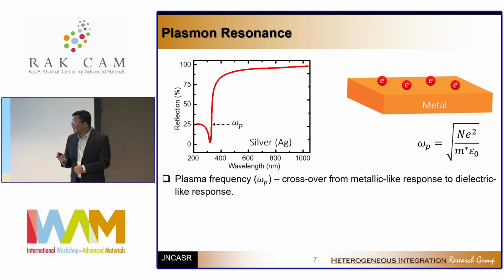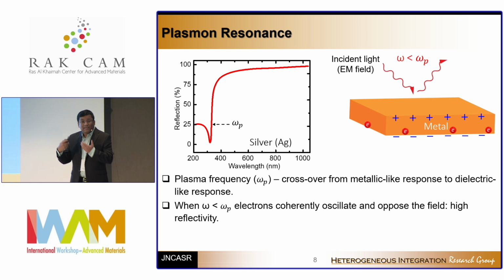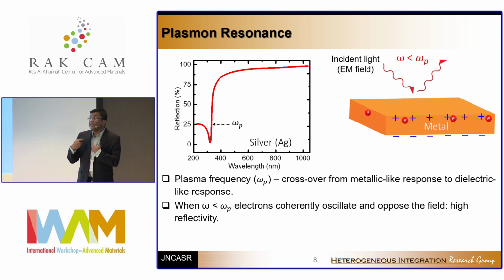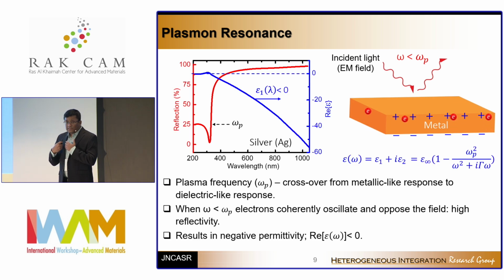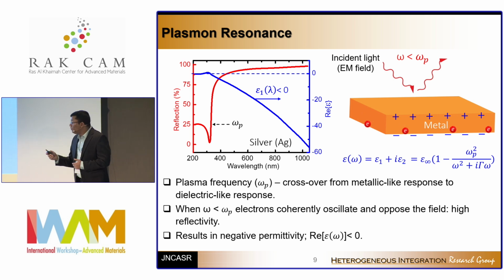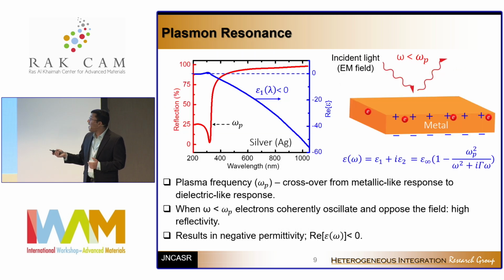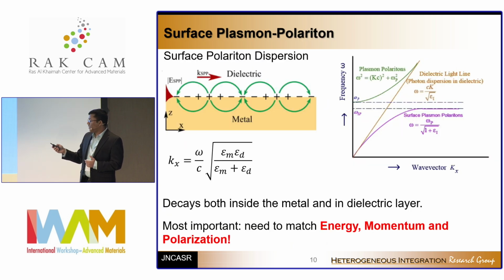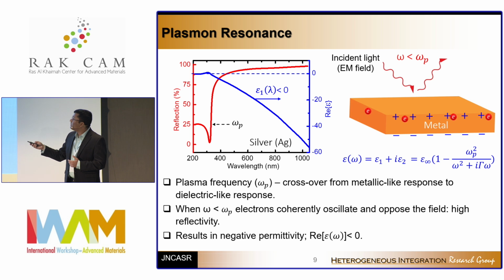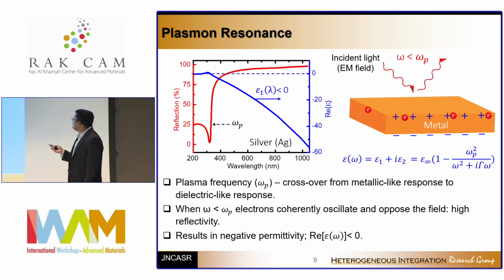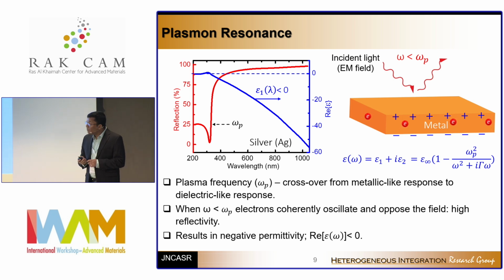electrons. And when you shine light on a metal, they start oscillating opposite to the electric field. They impede the electric field, and as a result, light basically cannot go through the metal, and it reflects back. And the frequency at which it reflects back, or the maximum frequency at which it reflects back, is basically known as the plasma frequency, or in some approximation, it is also known as the epsilon near zero frequency here. And the Drude model works pretty well in explaining the optical properties of metal.